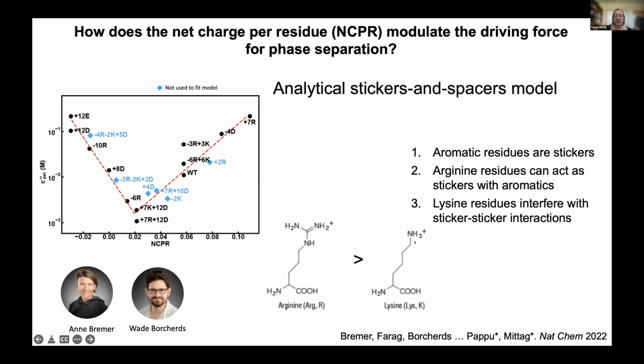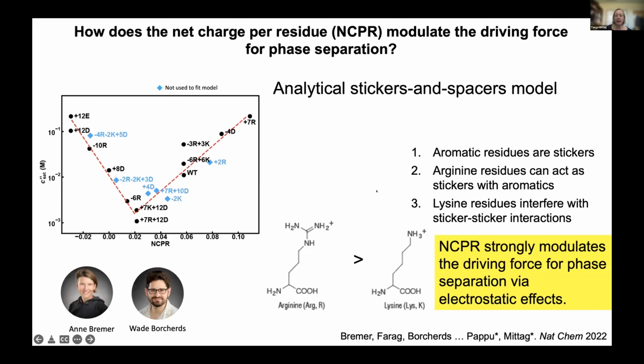And obviously, arginine and lysine have quite different properties. We have the guanidinium group in the arginine, where the charge is delocalized, and therefore the arginine is much less soluble than the lysine, where we have the point charge, and that really interferes with these cohesive aromatic interactions. We also really learned that the net charge per residue strongly modulates the driving force for phase separation via electrostatic effects, and hereby, 3 orders of magnitude.